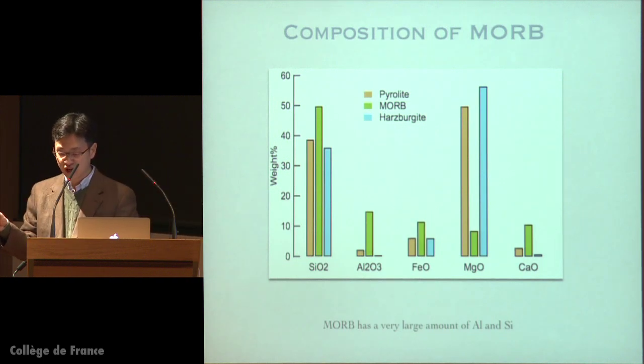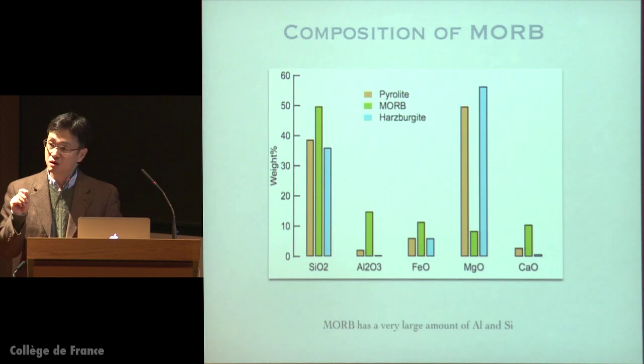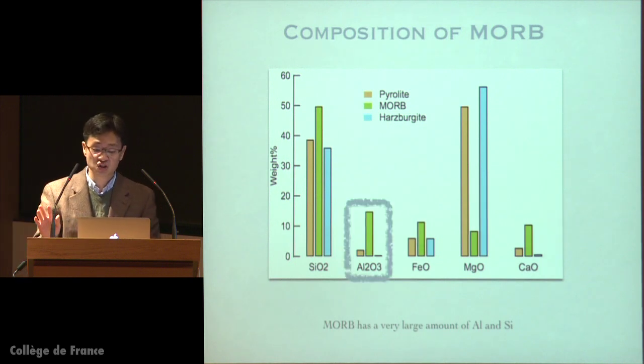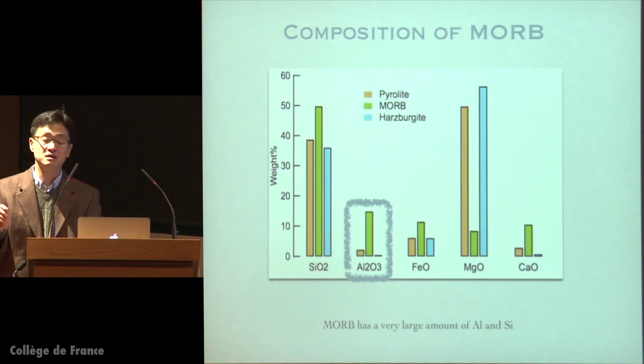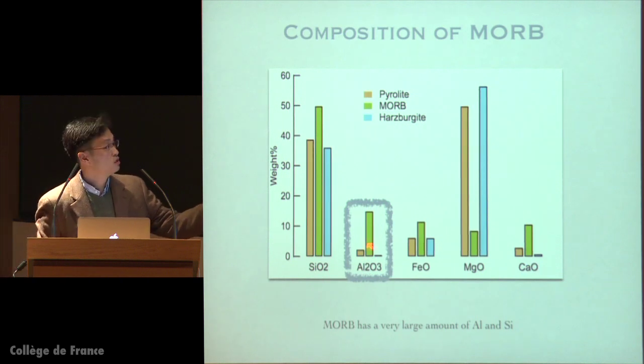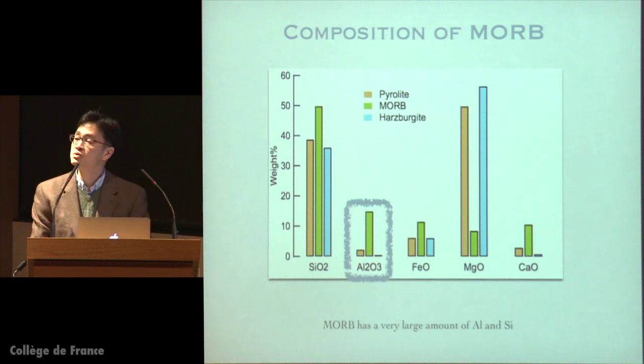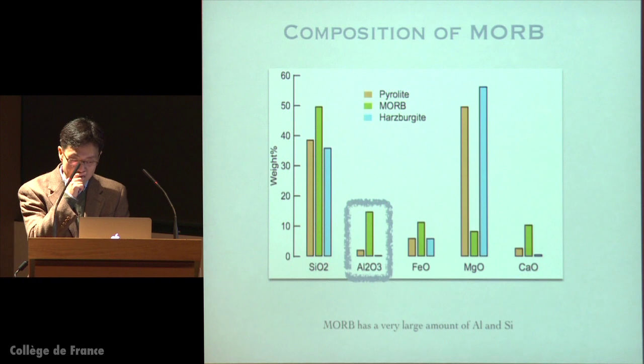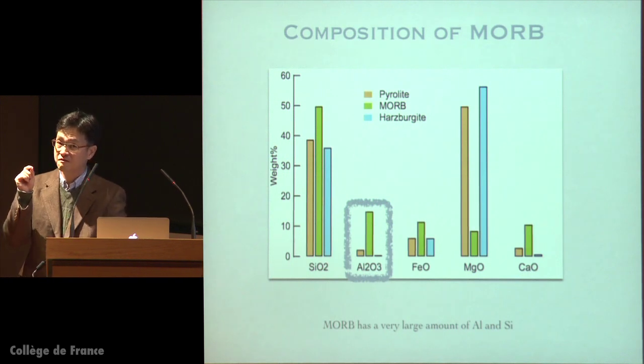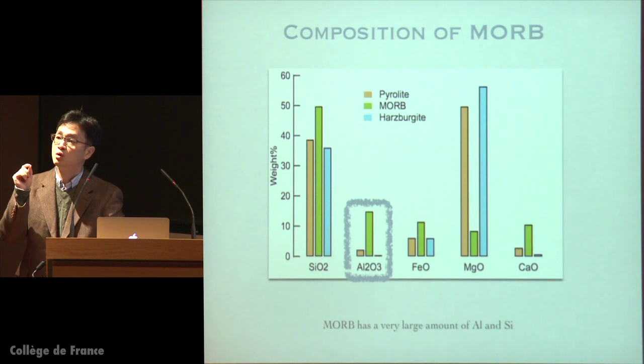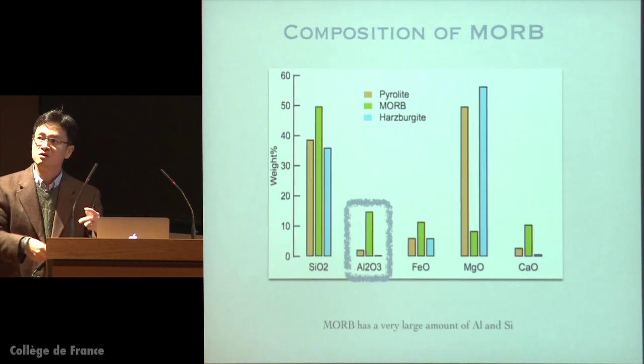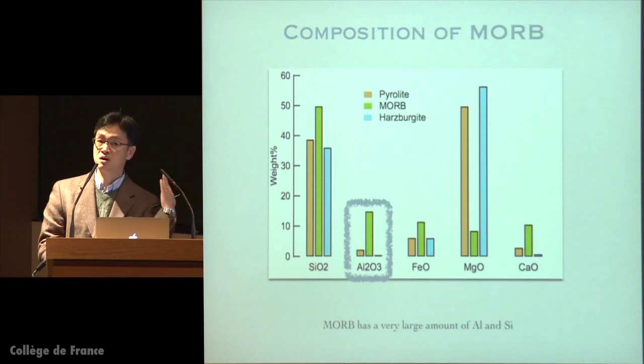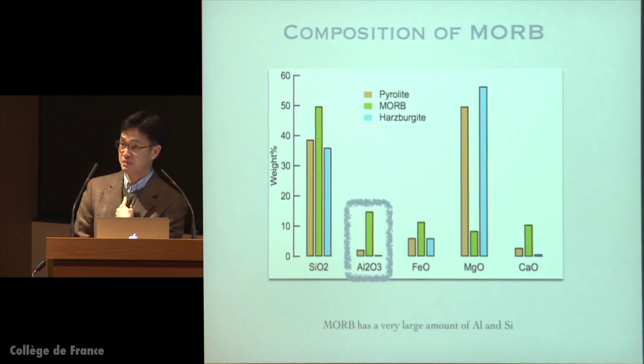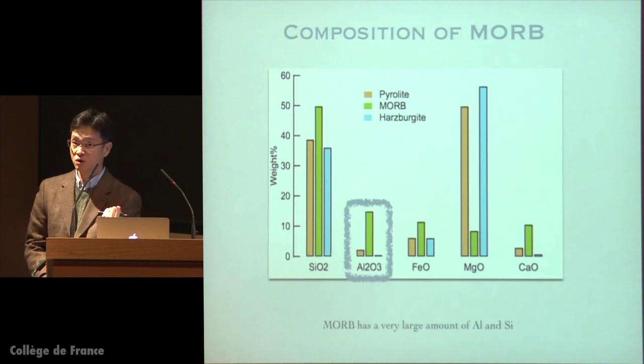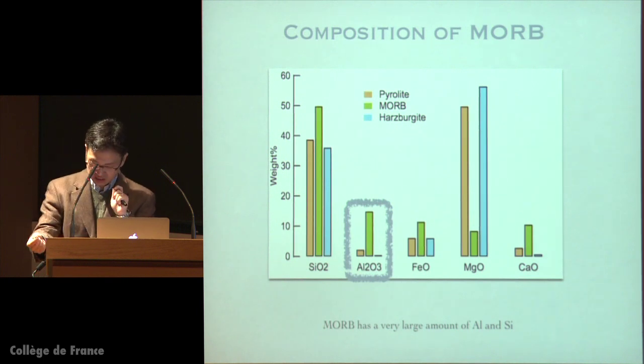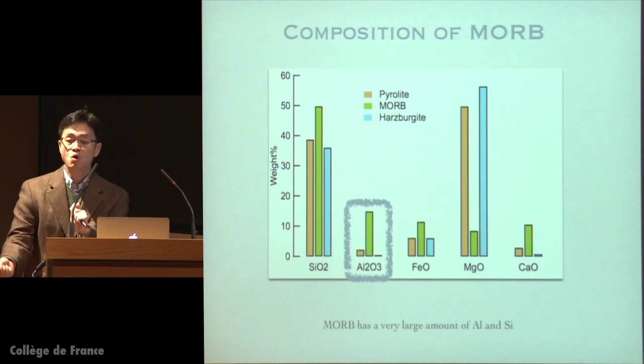So now I'm going to show you the data on morb composition. One thing that distinguishes morb from other compositions is the fact that morb contains a lot of aluminum. Here the orange represents the pyrolite and green represents morb or basalt. It turns out that in morb you have about a factor of 3 to 7 more aluminum than pyrolite. So out of the results that I showed already, you might expect, and we also expected, that the aluminum in morb would increase the thickness and the depth of the post-perovskite even more than pyrolite.